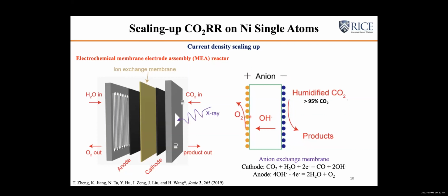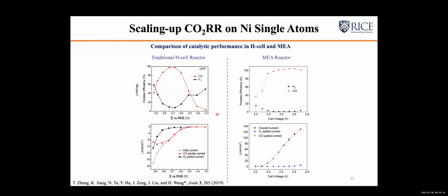But in this case, that OH crossover will get oxidized, generate oxygen. So you completely flip over the concentration ratios between water and CO2. Before, it was 0 point several zeros of CO2 percent, right? Now you have 95% of CO2. Using the same single atom catalyst, exactly the same catalyst, but in each of these different reactors, now you see a completely different